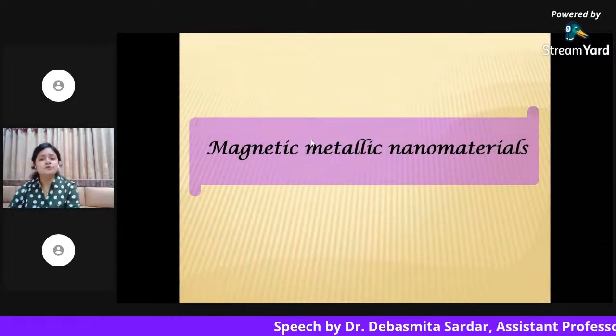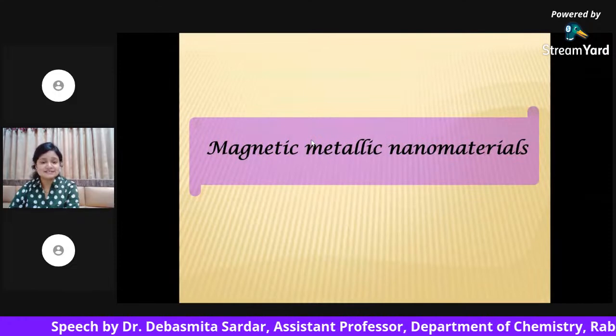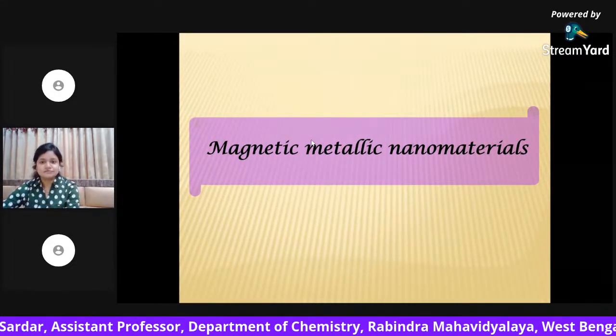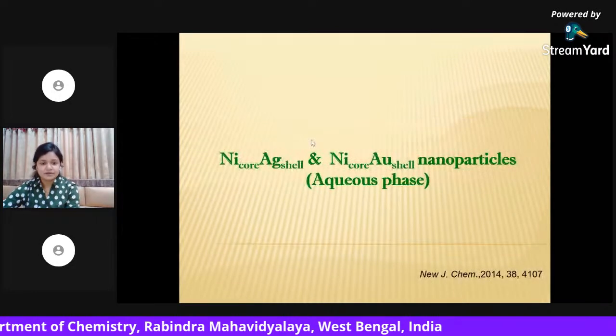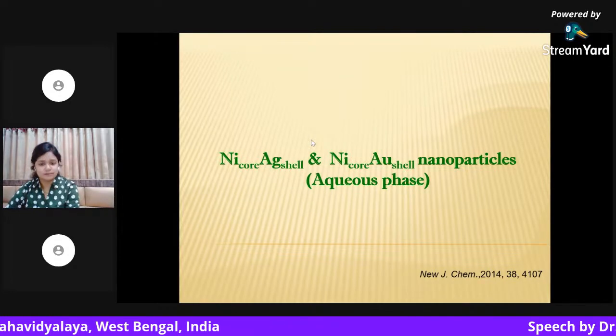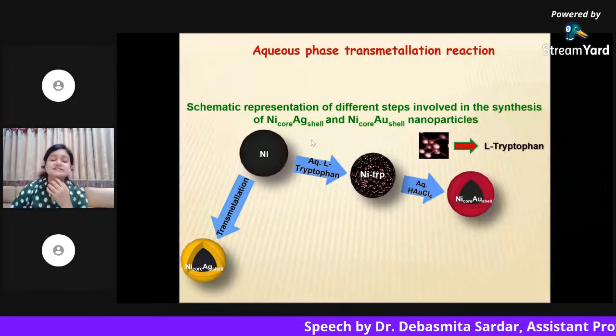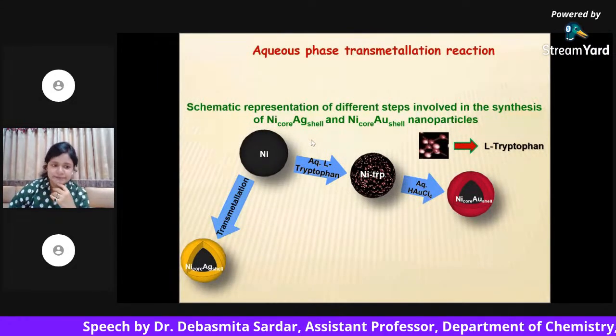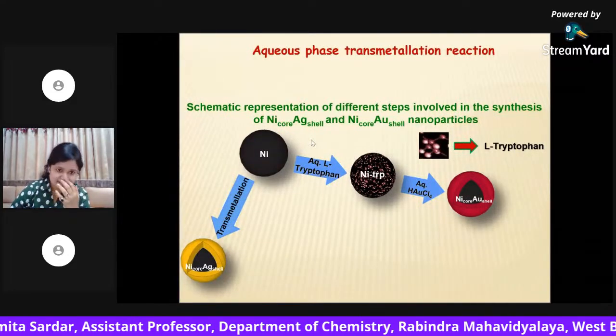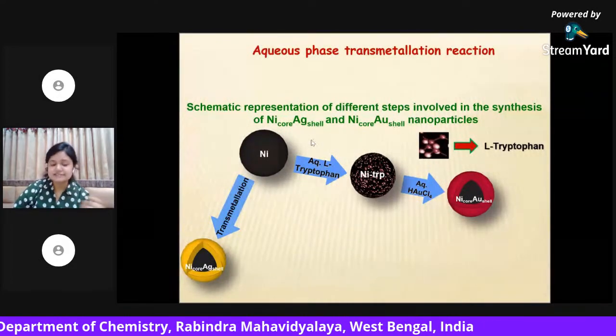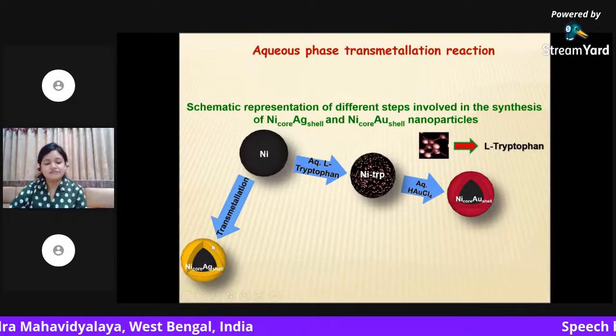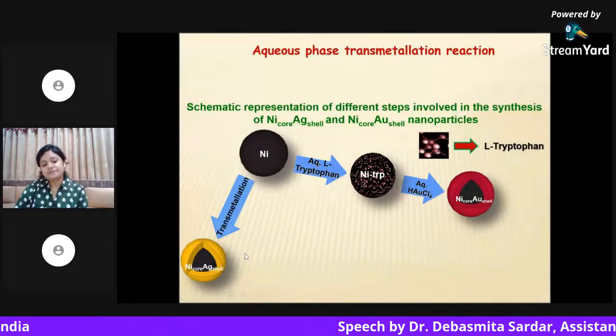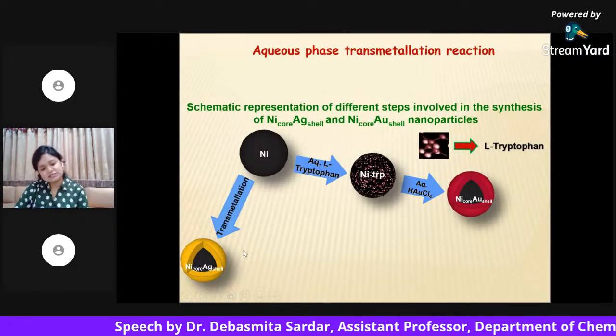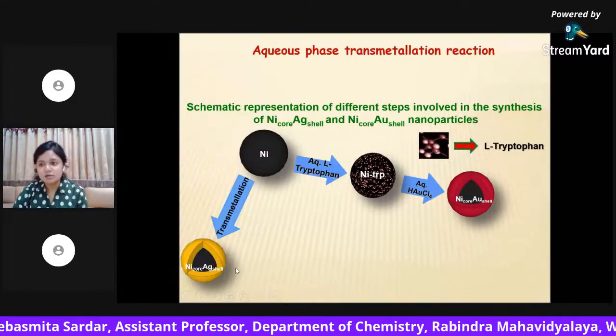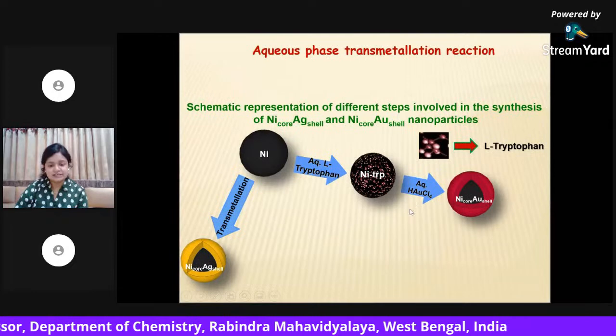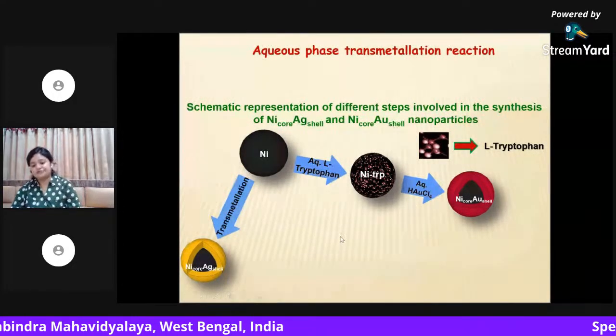So now I'll come to my research work, where you can see some real nanoparticles which I have synthesized in my lab. The first one is nickel silver and nickel gold nanoparticles in aqueous phase. This slide depicts the schematic representation of the different steps involved in the synthesis of nickel silver and nickel gold nanoparticles. Here you can see that the left one, nickel silver nanoparticles, can be formed via transmetallation reaction, and it is a one step reaction. And the right one, the nickel gold nanoparticle, can be synthesized by a two-step reaction with a surface modification with tryptophan.